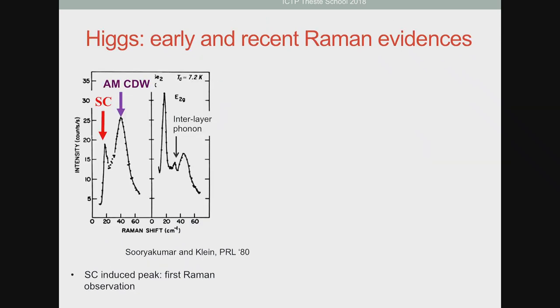OK, so what happens, and historically, this was the first time the coupling to the Higgs mode in a superconductor was evoked, was that when you cool down below TC, and this is sort of the first measurement where you could actually see the signal, the Raman signal from a superconducting phase. This was on niobium diselenide, so 1980 by Sooryakumar and Klein.